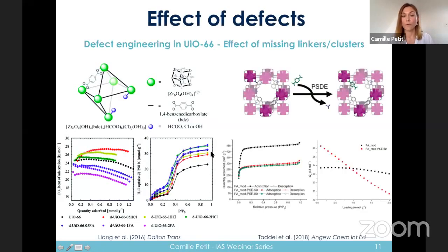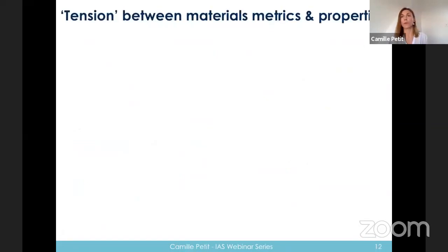This is somewhat confirmed if, instead of having a missing linker, we have for the same MOF here a missing cluster. We will have a change in the porosity, and that is what you see here with the nitrogen sorption isotherms. We have a change in the porosity, and we also have a change in the heat of adsorption, which is for CO2 here. So basically, you see that by changing either the structure or the porosity or the chemistry, we will have an impact on those materials-based metrics that I was mentioning earlier.